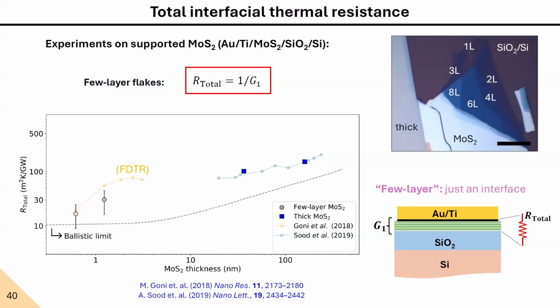And the difference between our results and these experiments is that they used a sister technique to do these measurements. These are frequency domain thermoreflectance measurements, so using continuous wave lasers and resolving in the modulation frequency of our pump, instead of using pulsed laser systems and looking at it with time resolution.